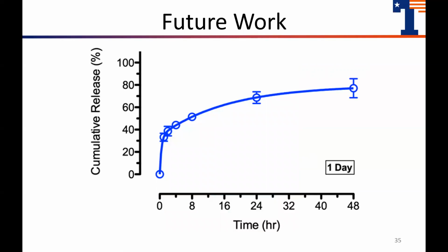So this is the original drug release graph. And for hypothesis 1, if it is true, we're expecting to see a faster drug release here. So it'll probably be a higher rate in this section here, and probably would level out more, be higher overall. And then if hypothesis 2 is more correct, we expect it to be very similar to the one shown. And we might end up having something in between. It might have a faster drug release, but also be very similar in the end section. And this means that both of them are occurring at the same time, and we should be able to see which one is occurring more throughout the process.